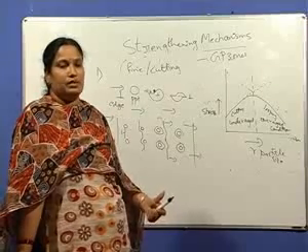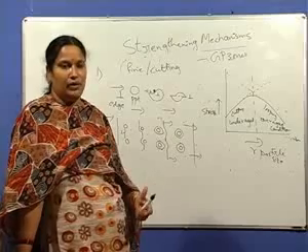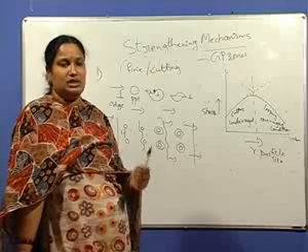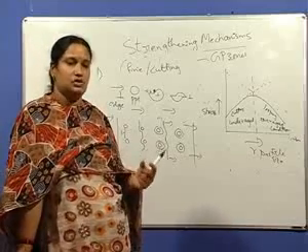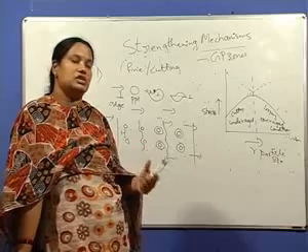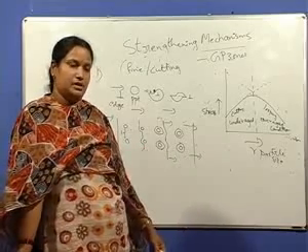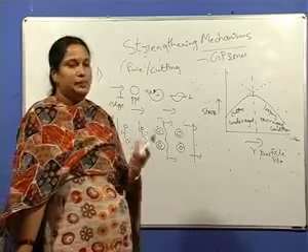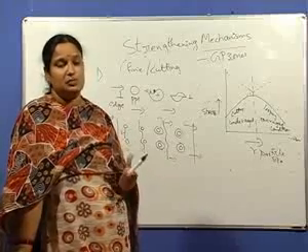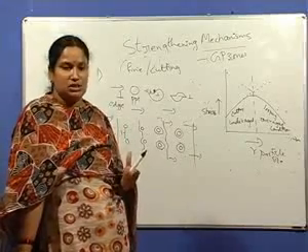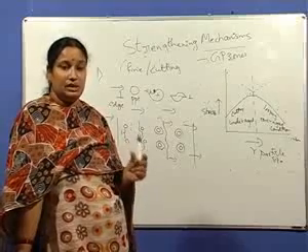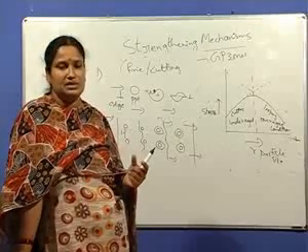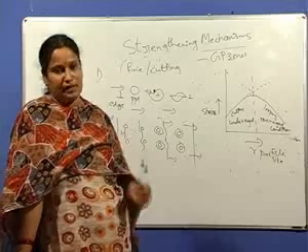It can be made because it is simply mechanical alloying, mixing of metal matrix powders and inert oxide powders in a high energy ball mill, followed by compaction and consolidation by powder metallurgy techniques. One more difference is that in precipitation strengthening alloys, the precipitate is coherent with the matrix, whereas there is no coherency between the dispersoid and the matrix.